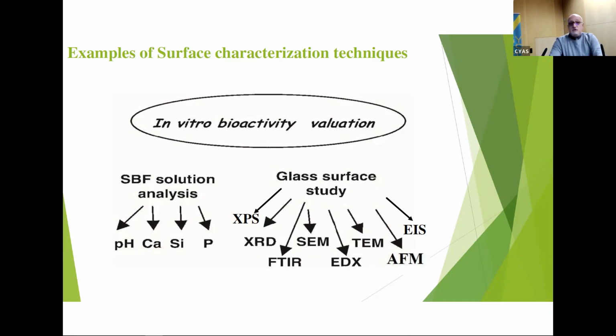XPS, XRD, sometimes you have to use XRD, X-ray diffraction, FTIR, that means infrared, SEM, that means scanning electron microscope, EDX. EDX means that when you are looking under the microscope and you have some grains, I will show it later with the next slides, you make some X-ray on your samples under the microscope to get information about what type of grain you have.